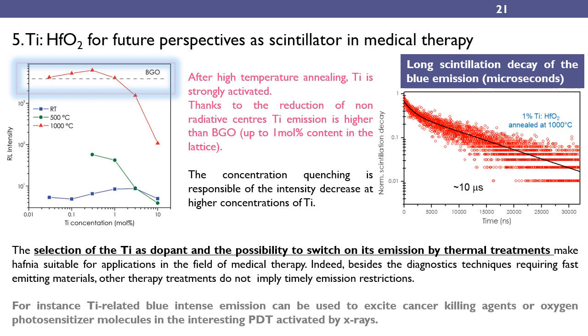Despite the very high intensity in the blue region, the long scintillation decay time is not suitable for use in fast timing techniques. Nevertheless, new medical treatments require the use of scintillating materials without implying strict requirements in timing performances. For example, the blue titanium radioluminescence emission can activate cancer-killing agents like oxygen photosensitizers for photodynamic therapy activated by X-rays.